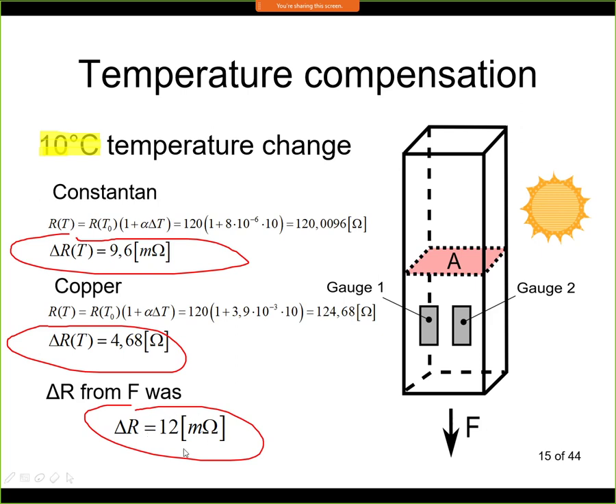And remember that initially we had 12 milliohms from the force. So from the force our signal was 12 milliohms. We have changed the temperature just by 10 centigrades, and the signal from temperature is about the same size. And here for copper it's completely hiding this signal, so we are not able to use this copper strain gauge